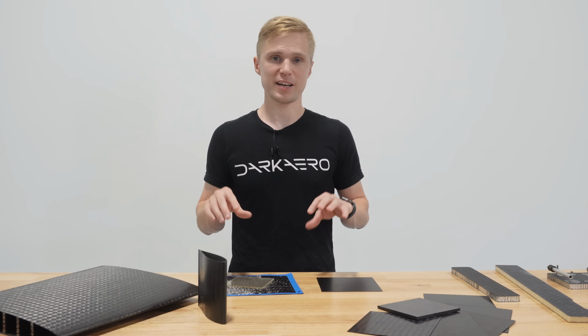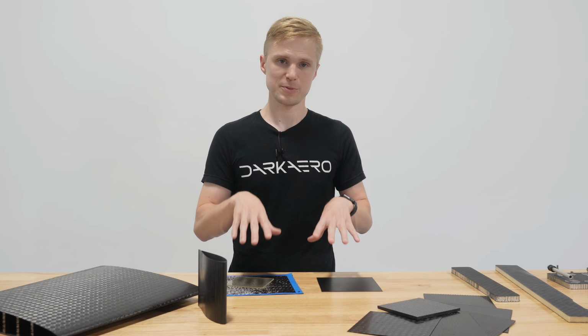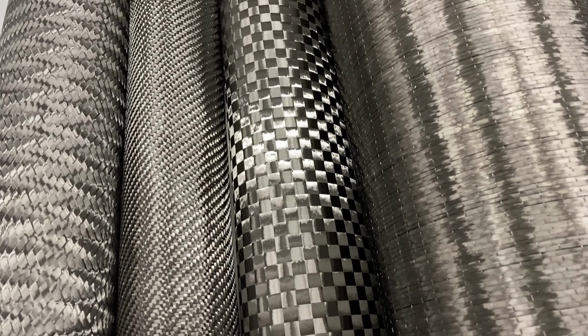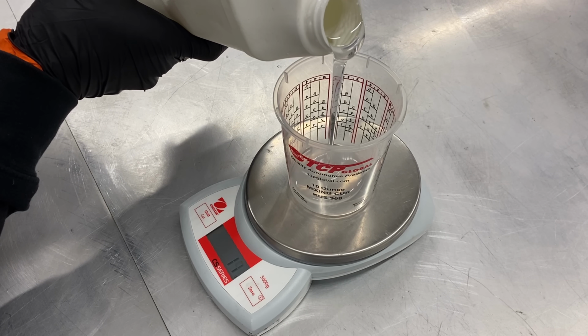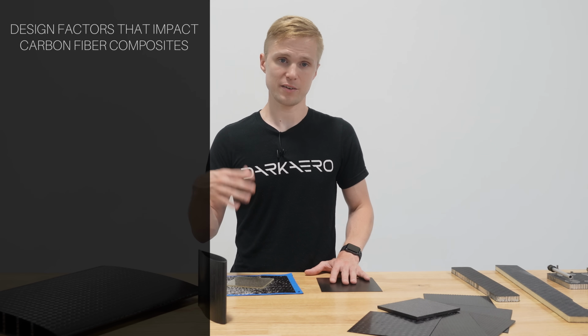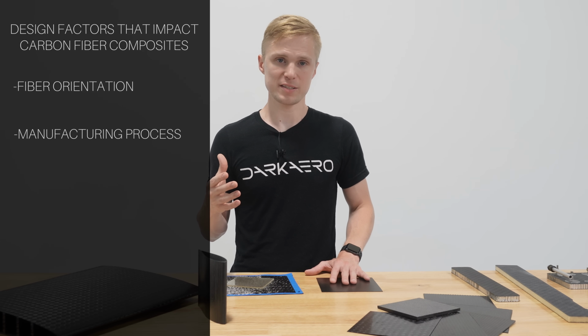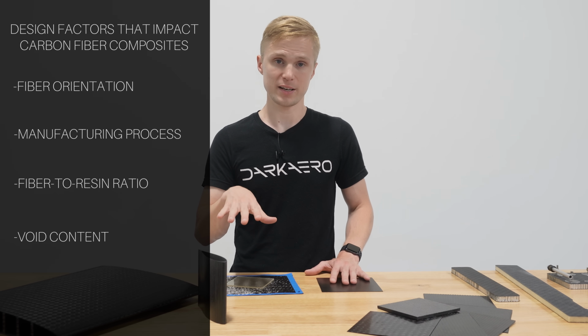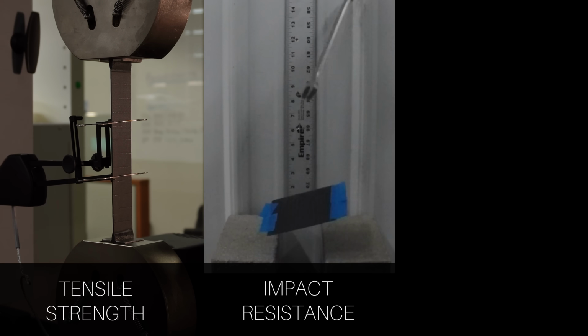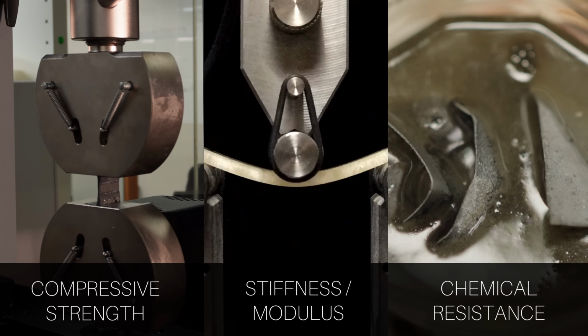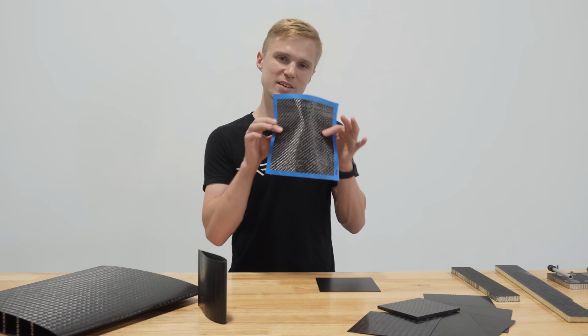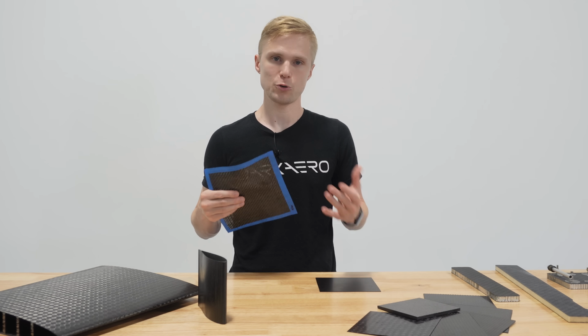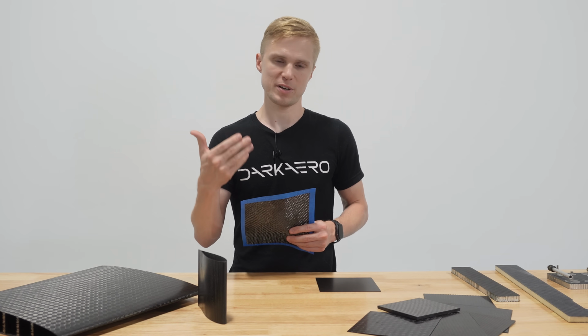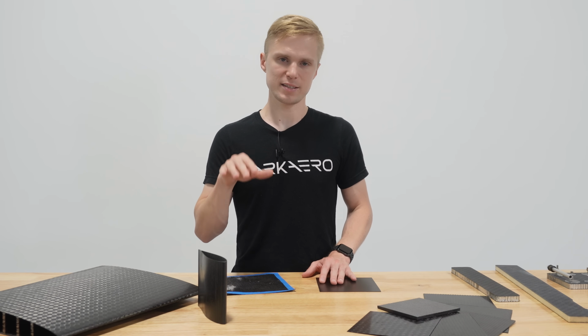There are a ton of variables that go into determining the properties of composite materials like carbon fiber. Naturally, these include the fiber type and resin type, but beyond this, other factors like fiber orientation, manufacturing process, fiber-to-resin ratio, and void content also play a role. These variables will affect the tensile strength, impact resistance, temperature capability, compressive strength, stiffness, and chemical resistance of a carbon fiber composite part. If we focus just on the carbon fiber from a single manufacturer like Toray, a range of fiber grades can be found. Different grades have different strengths and stiffnesses.